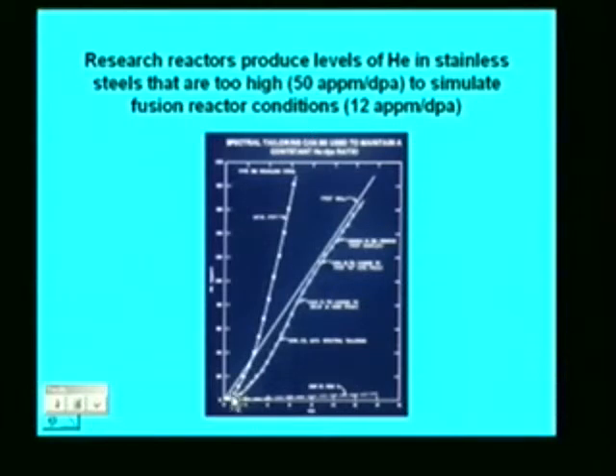Well, here we've plotted a line with a slope of 12 showing the desired production rate for fusion. And now we want to be clever about producing the right amount in a simulation. And what's done here, this particular irradiation is for the ORR, the Oak Ridge Research Reactor. We start with our materials just surrounded by water to burn in nickel 59. Then, before it gets too high a concentration, the core piece is replaced to displace the water. So we put aluminum in place of the water to harden the spectrum. And then, a little further on, it has to be replaced by hafnium to absorb the thermal neutrons to get the helium production under control. And at that point, it will track the correct helium to dpa ratio. So this is one of the techniques, one way that we use the fission reactors to simulate fusion reactor behavior.